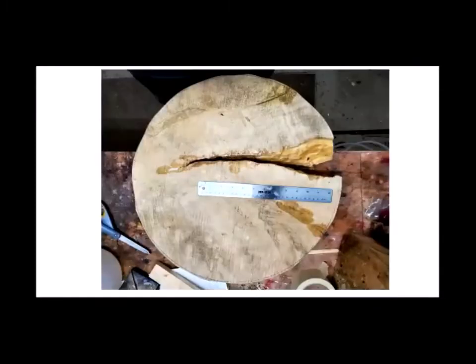So I took this, and the one thing you need to do is you need to make sure you get all the bark off where that crotch piece is. Epoxy, none of these resins will like to stick to bark. Even if it does adhere to it, the bark isn't adhered to the substrate very well, and you're going to end up with a problem. So you have to remove the bark, whether it's burl or a crotch or whatever you're doing.